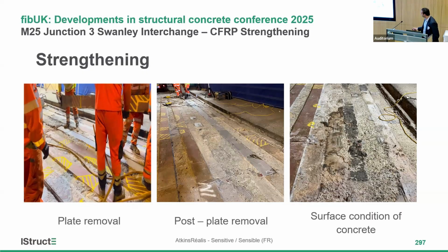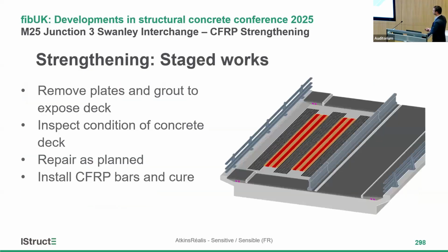And this is the post plate removal at the location and close inspection of the surface condition of concrete. Because we had to maintain minimum structural capacity of the structure, the strengthening had to be carried out in sequence as well, where only part of the plates were removed. And at those locations, the FRP was installed because this carriageway was live, carrying traffic.